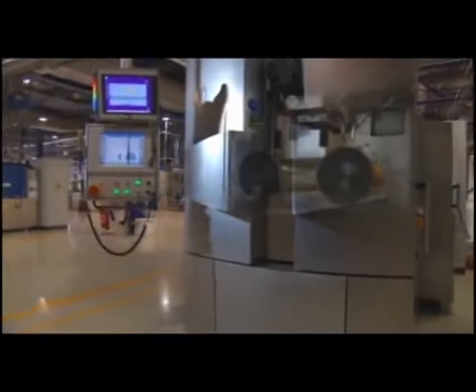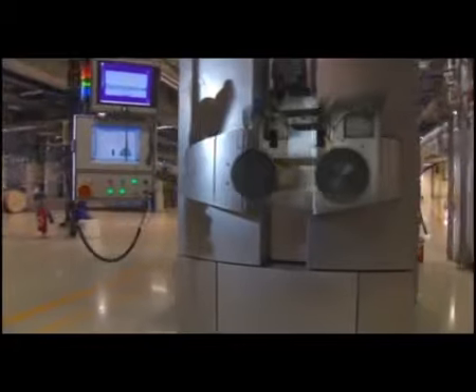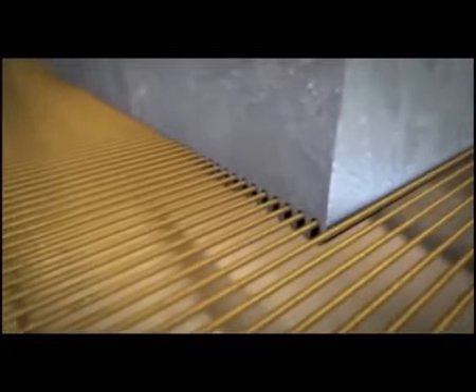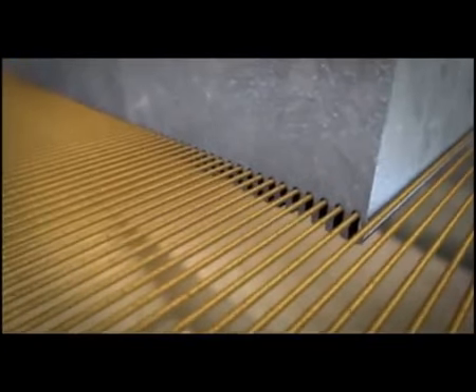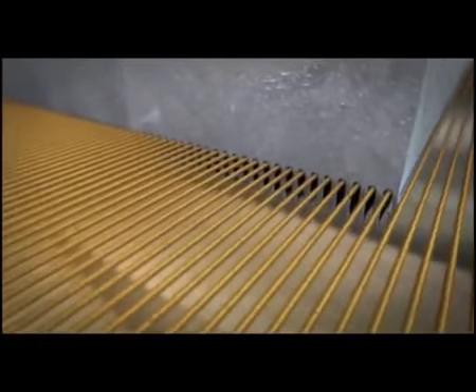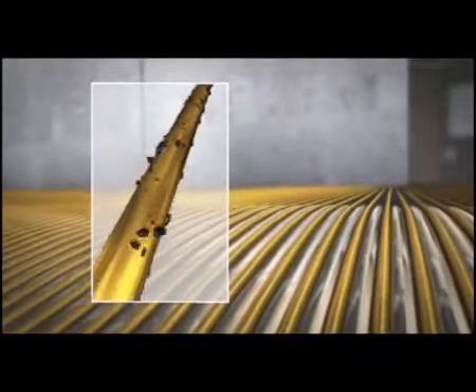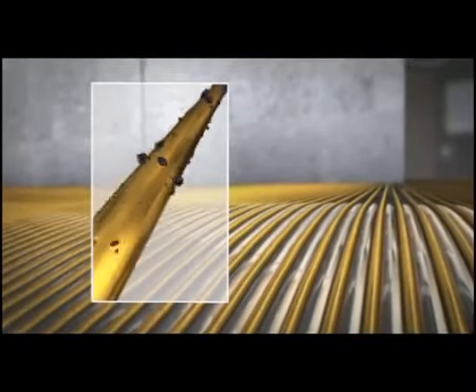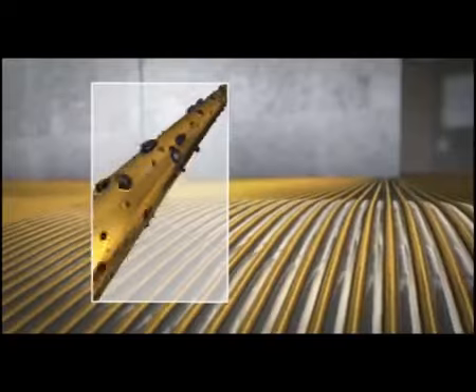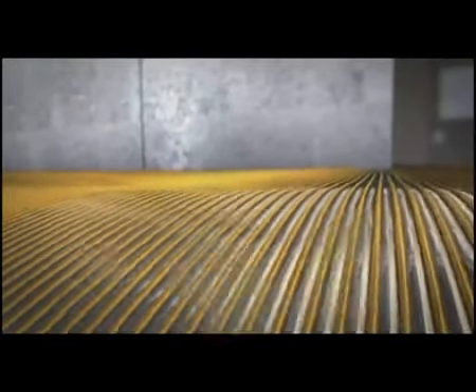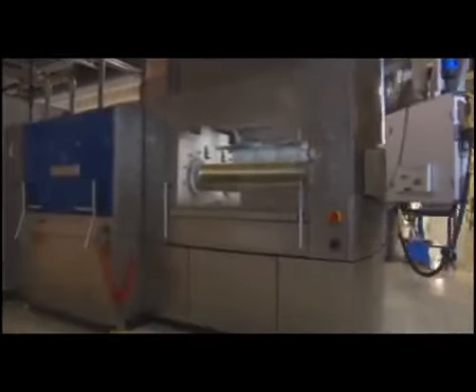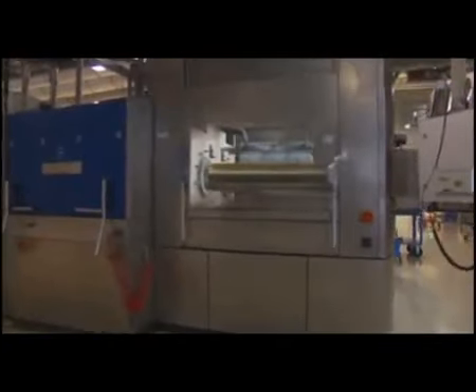The high-tech saw is equipped with two large track rollers. In contrast to the briqueter, a special wire of roughly 700 kilometers length runs across it at high speed, creating a rotating wire field through which the silicon bricks are pushed. The wire transports slurry. Its fine particles slice the silicon brick into wafers that are approximately just 0.2 of a millimeter thick. After approximately 8 hours, the plant has produced between 2,000 and 3,000 wafers.